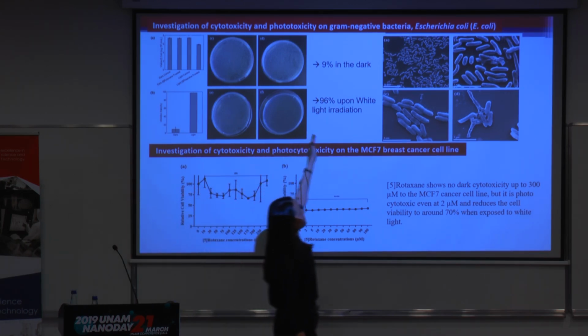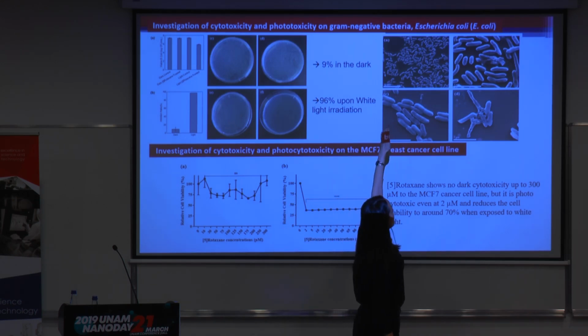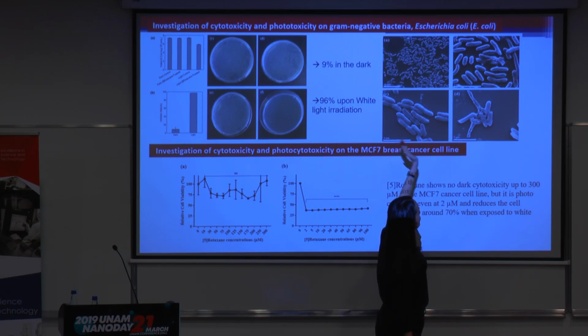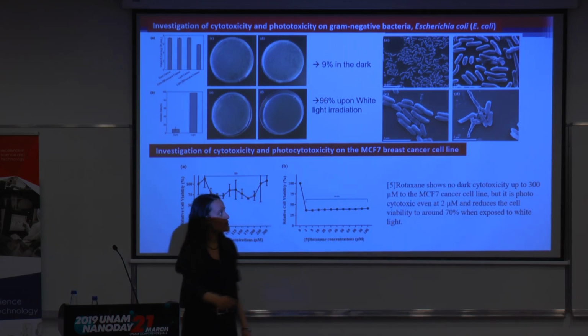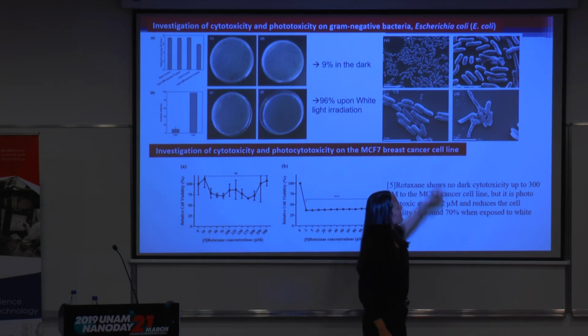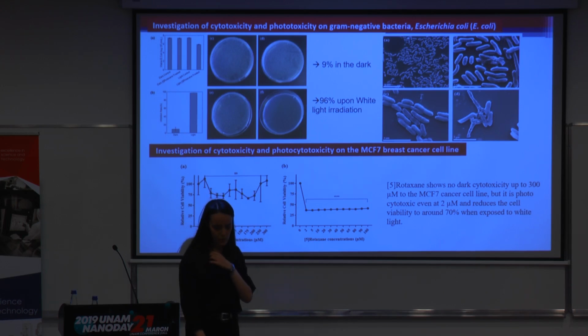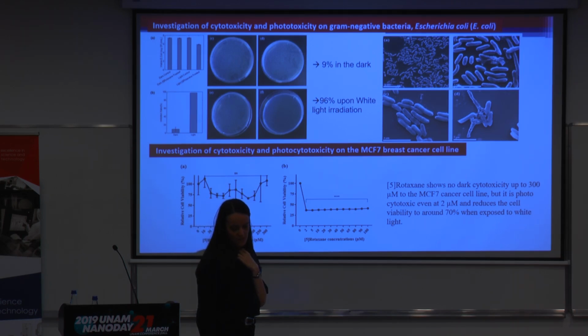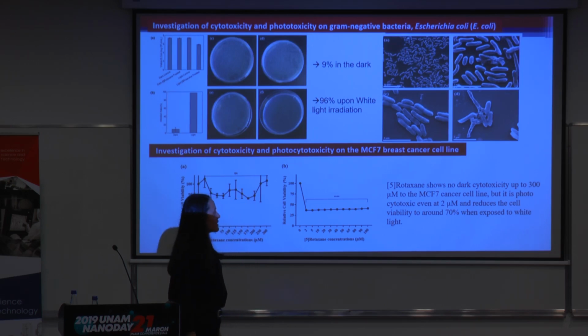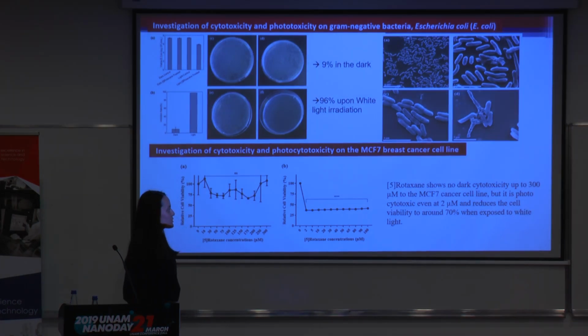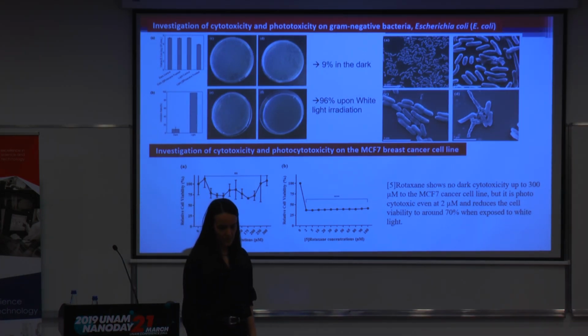And these are our SEM pictures. A and B are dark. The left side is control, the right side is with sample. As you see, in the presence of light, the cells of E. coli are destroyed. And it's a good thing for our supramolecular photosensitizer that the effect in the dark, the cytotoxicity, is diminished. And also we did the same experiments using the MCF7 breast cancer cell line. It doesn't show any cytotoxicity at 300 micromolar, but even 2 micromolar is enough to inhibit that cell line.